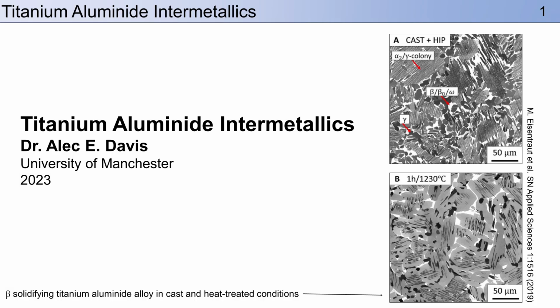In conventional titanium alloys, you won't usually see more than 6 weight% aluminium additions, since second phases start to form that are generally unwanted. However, when you make an alloy that is nearly half and half titanium and aluminium, you create a material that has desirable high temperature properties, but can be a little awkward mechanically. These alloys are known as titanium aluminide intermetallics.